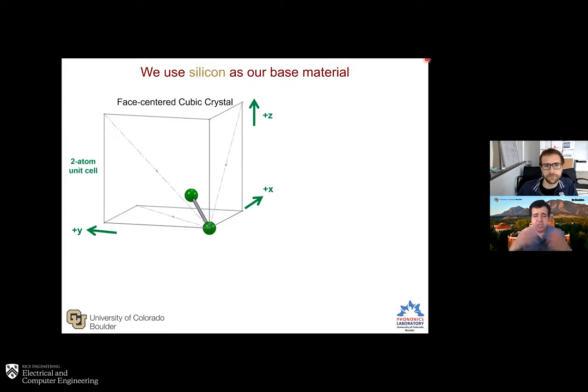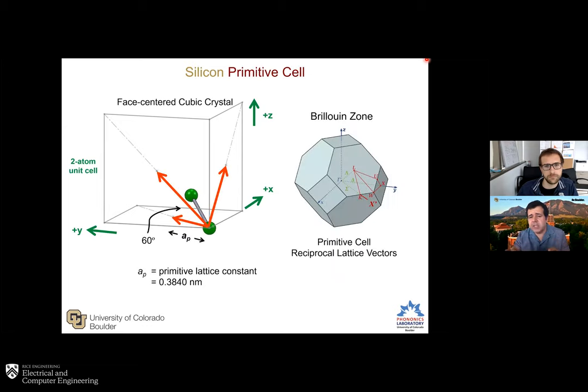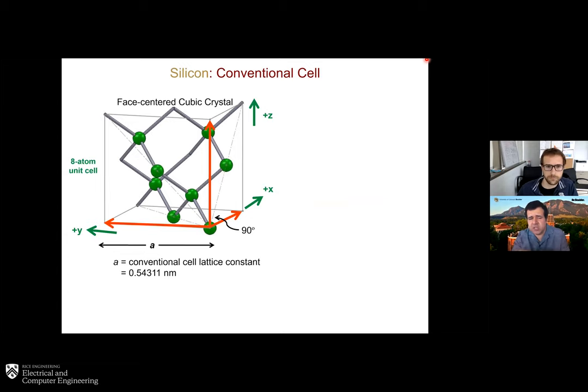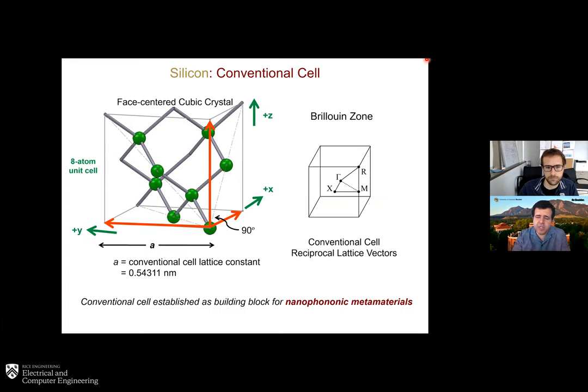So from the modeling perspective, we essentially have to model at the atomic scale, because if we, for example, use a continuum model, we lose much of the physics. So starting at the atomic scale, we take two atoms, which represent a primitive cell in silicon, and we can build our model based on primitive cells. The challenge, though, is that its Brillouin zone is quite complex because the primitive lattice vectors are oblique, at different angles and so on. So we take a small step and instead work with a conventional cell where the lattice vectors are all orthogonal. So in the reciprocal lattice space, we have quite a workable Brillouin zone, just a cube that we can use as a building block. And you can see here the irreducible Brillouin zone marked in this conventional cell.